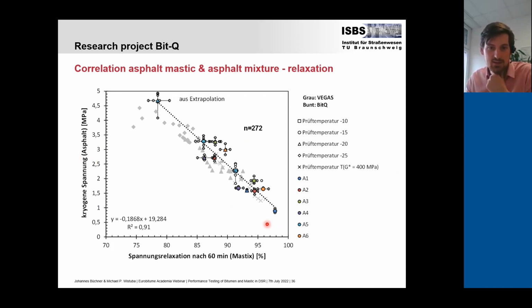Here we can see very nicely that the fit of this linear regression is very solid. Again, you can also see the number of individual experiments: there are 270 individual experiments, since we have a lot of replicates displayed here, to check whether the outcome is really solid or not. The regression coefficient here was 0.91 for this data, so we were quite happy to see that the whole methodology also works for these plant-produced mixtures.